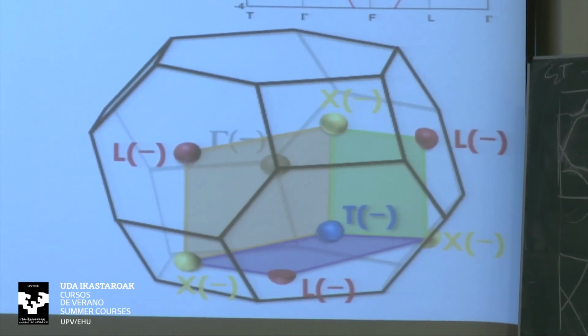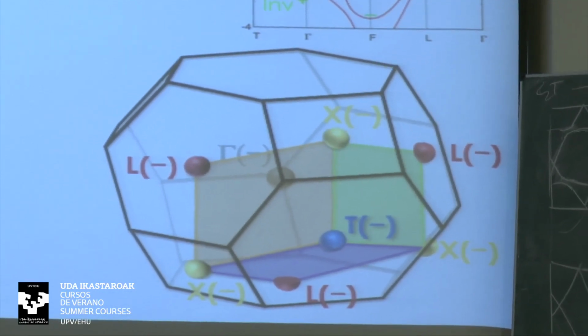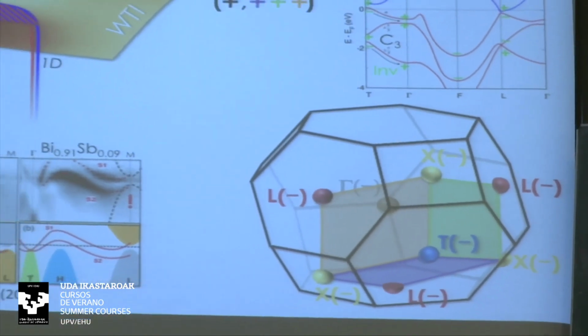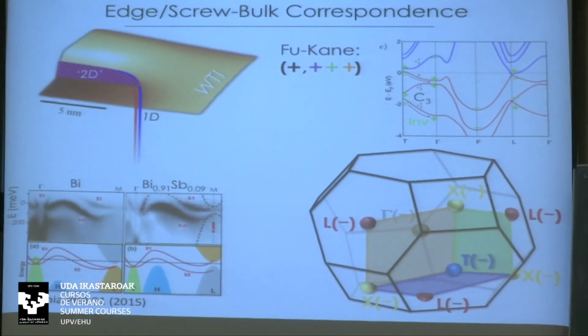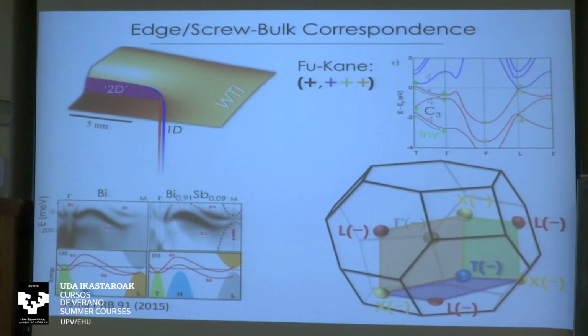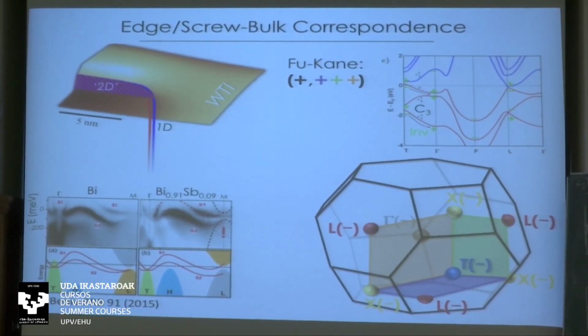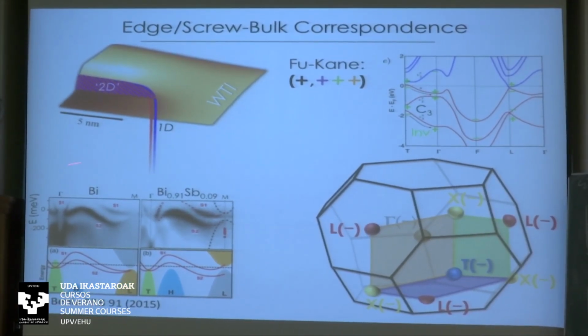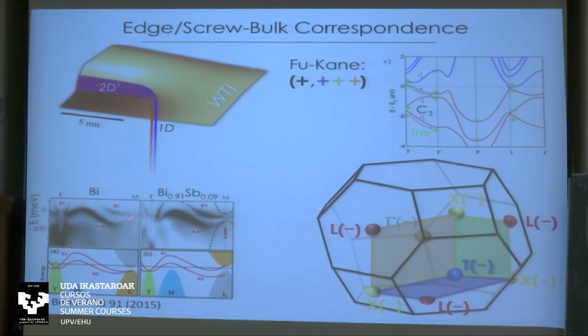However, as we've said before, the L gap is tiny. So if you look at all the ARPES measurements and all the studies, there's even debate about the sign of the L gap, but we're not actually questioning the sign of the L gap. If you just look at the ARPES data, first of all, M is the surface projection of the bulk L point.